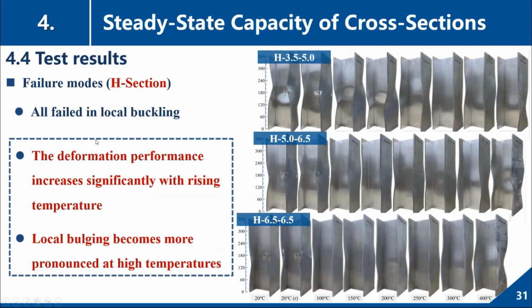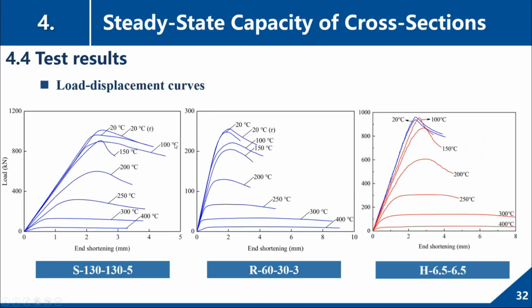And for each section, all of the specimens failed in local buckling. The deformation performance increases significantly with rising temperature, and the local buckling becomes more pronounced at high temperatures. And these are the load displacement curves.